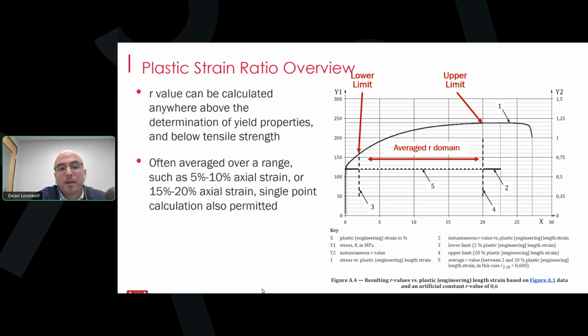Now, R value can either be reported from a single location, for example, when tensile strain equals 10%, or it could be calculated over a range like 15 to 20%. The specific requirement here is typically determined by the metal former, as they'll want to know the R value over the expected strain domain used in the manufacturing process.